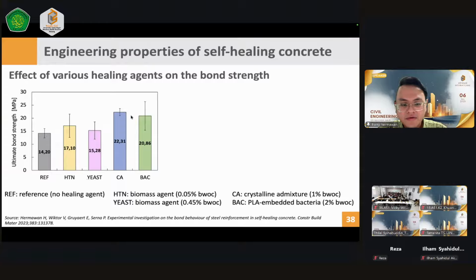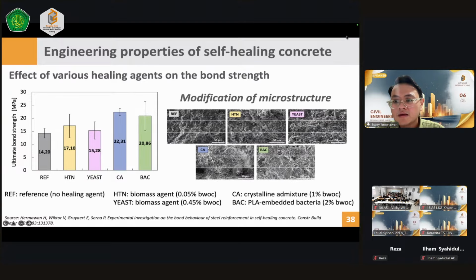But if you compare now with the crystalline admixture with the blue bar and also the green bar with the addition of the bacteria, it significantly increased the ultimate bond strength. You see, from the 14 MPa into 22 or 21. And why does it happen? If you want to know more about this, you have to go deeper into the microstructure of the concrete.